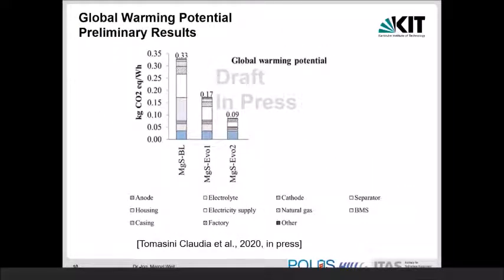Now to the other impact category, called global warming potential, GWP. That's the CO2 impact and the equivalents from other gases. And you see here more or less very similar results. The not optimized magnesium battery cell has quite a big impact, with this first optimization of the adjustment of the pouch.